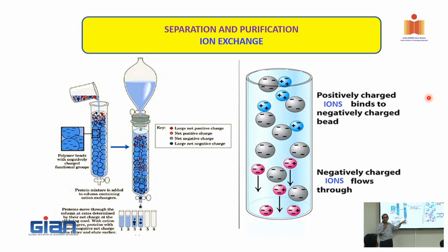The loading capacity is always expressed as that many grams per liter of wet settled resin. That is called loading capacity. Then you try to elute it. Whenever you are eluting, you don't have to use the same volume of water. You can use a reduced volume of eluent solution, so that by the time you collect it here in the eluate, the concentration will be improving from 1 gram per liter to 10-15 grams per liter. That many times the enrichment of the metal ion in solution takes place by this process.